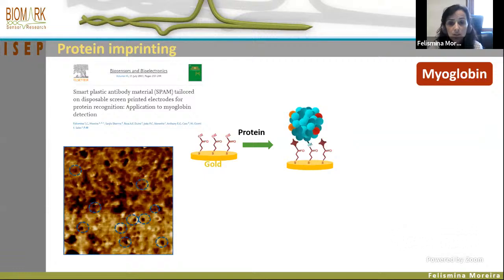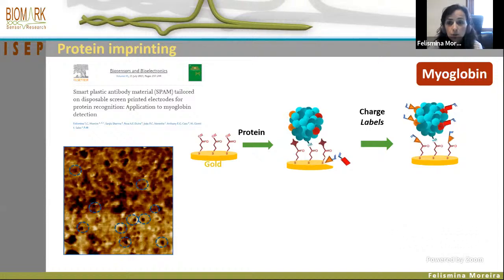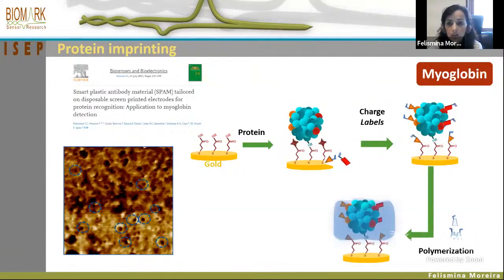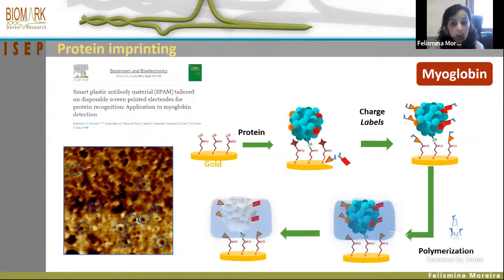The next step consisted in the protein covalent attachment. And we introduced for the first time in our group labeled monomers, positively and negatively charged, that will establish the binding sites for the imprinting. So the polymerization starts with addition of the monomers and cross-linkers, in this case acrylamide and bisacrylamide and ammonium persulfate, and the template removal was performed by action of one enzyme, in this case proteinase K.